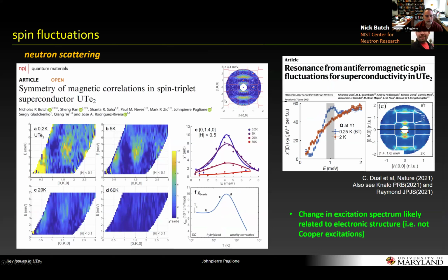Okay, moving on. Next controversy: neutron scattering. Okay, so neutron scattering, at least to date, there's 3 groups that have done inelastic neutron scattering, and I would say that their data essentially agrees in the sense that they see some intensity along the Brillouin zone edge, which is along the B-axis edge. So you see here, and then it's a question of interpretation.